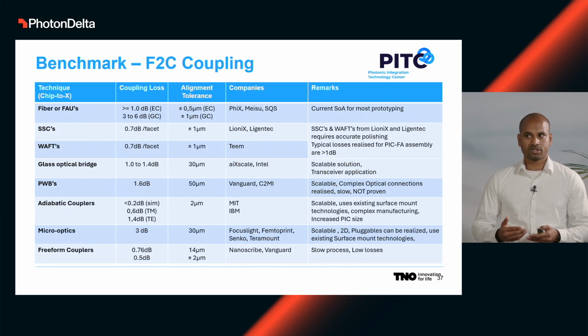There are also spot size converters from LioniX, Ligentec, and WAFTs that are provided by Team Photonics. There is also some research done by Intel and aiXscale on bringing glass optical bridges for scalable solutions. There are also very high alignment tolerant photonic wire bonds that have been introduced by Vanguard and C2MI, and adiabatic couplers, which provide lower coupling losses with a moderate alignment tolerance of about 2 micrometer.